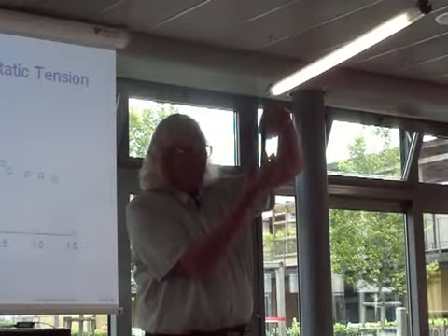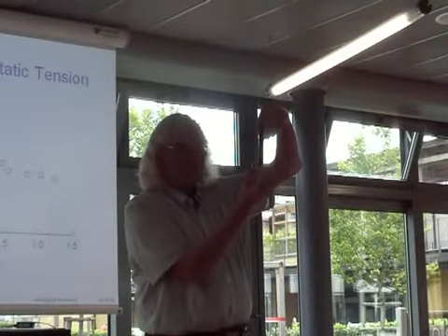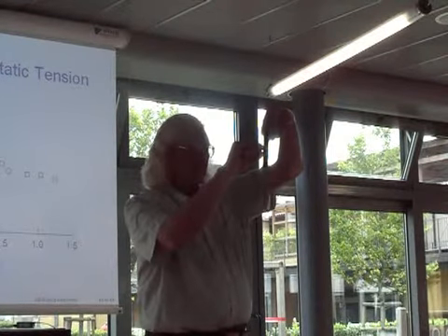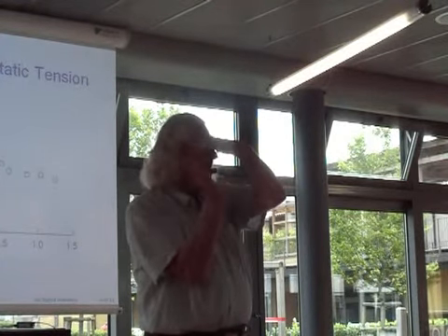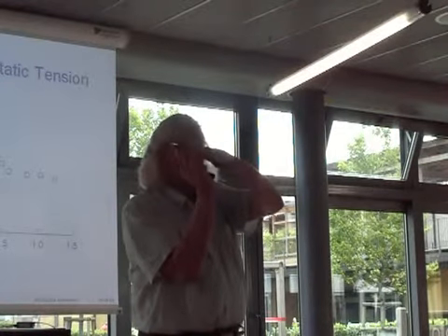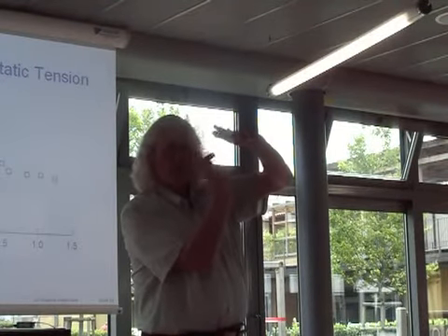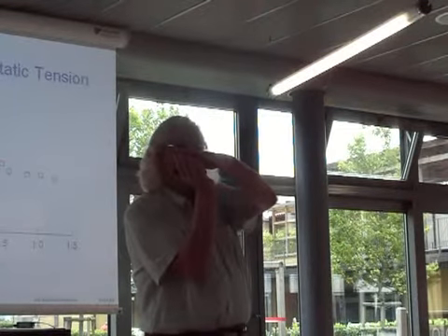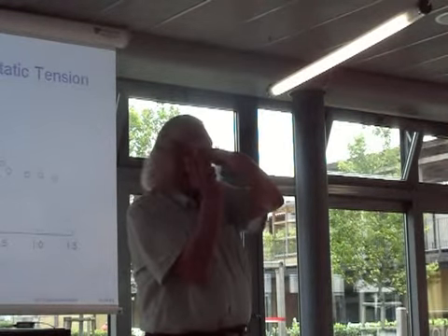And what happens if I pull this in tension? The small cracks that form here are going to be opened up. Remember my pictures about all that rubbing and so on. But if I apply tension, I will eliminate all of that friction. And so this should be very detrimental.